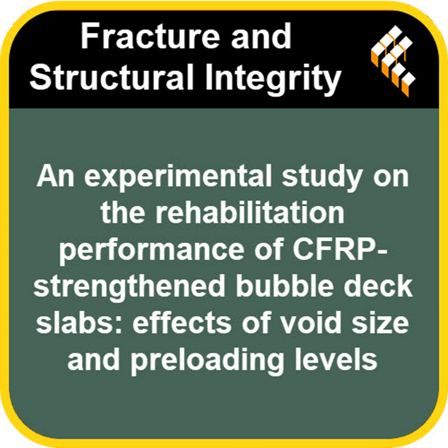Now, what about the 60 mm void slabs, group 2, with the CFRP? Was the outcome similar, or did the larger voids present a different challenge for the repair? The results for the 60 mm void slabs definitely told a different story, a bit more nuanced. While these also showed recovery, their ultimate load increased by 5% to 9% compared to their unreinforced state. The percentage of recovery relative to the solid control slab was generally lower, especially for the more severely damaged ones compared to the 50 mm group. Okay, so the repair wasn't quite as effective overall. Less effective in terms of reaching that solid slab benchmark, yes.